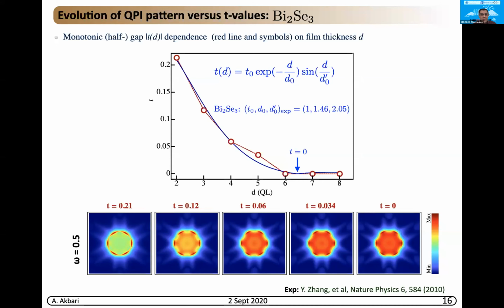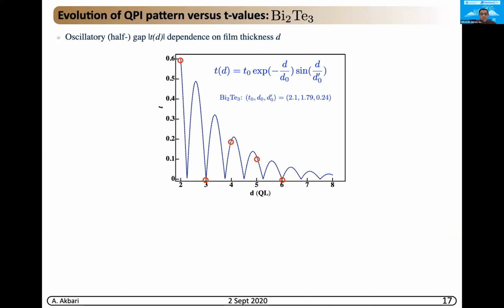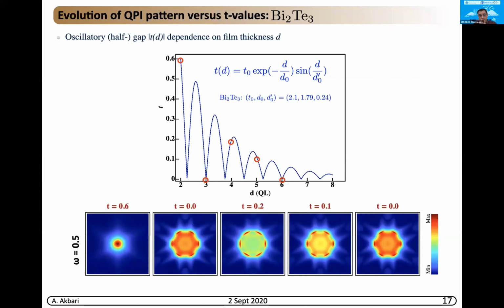But for the case of bismuth telluride, we still don't have any ARPES data or other experimental technique to check the fitting parameters. From the theory, though, we know that we expect to see more oscillations, so I took this kind of fitting and then ran the QPI calculation for the same system. We see that it now perfectly shows the oscillation in the QPI feature, from the drop-like feature to a snowflake, and also the intensity of the QPI starts to change with increasing or decreasing thickness.